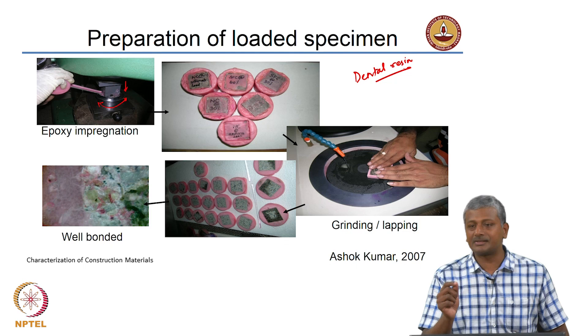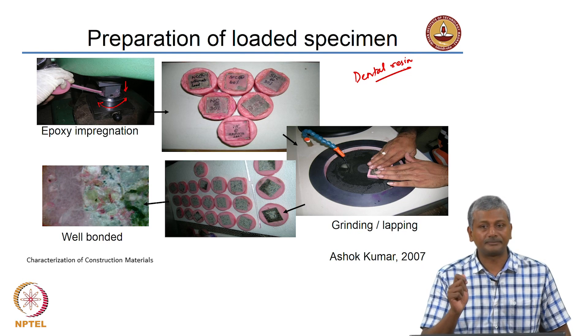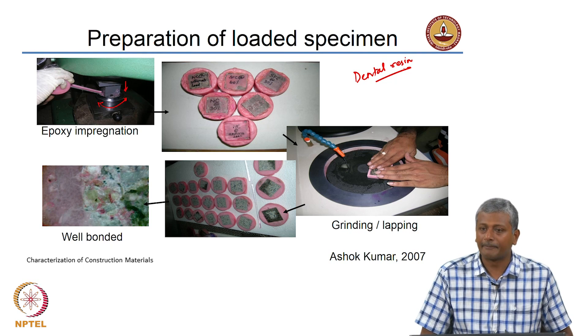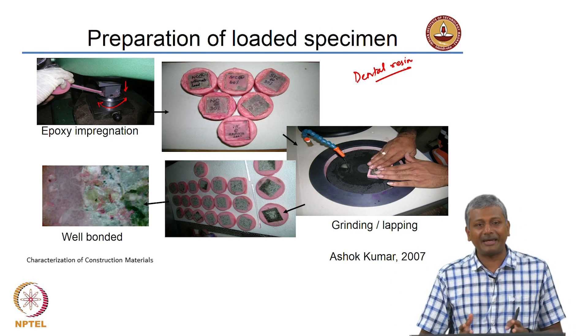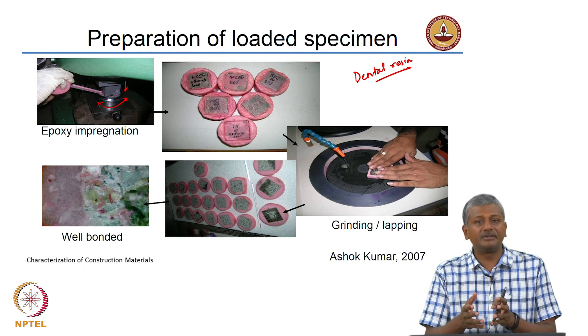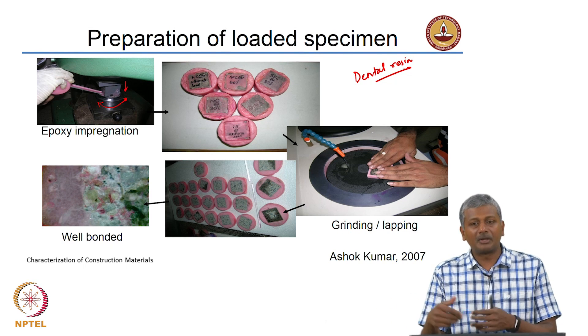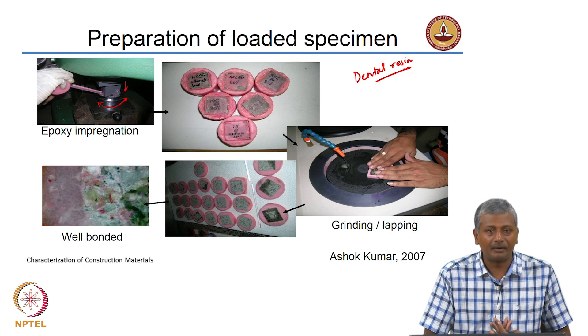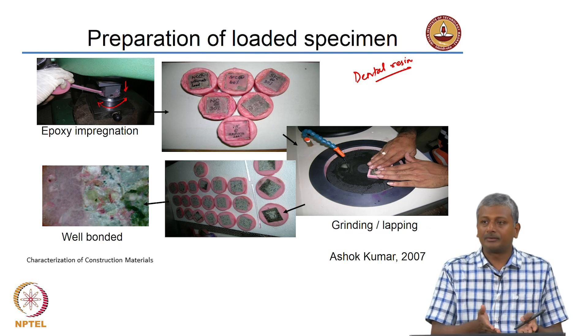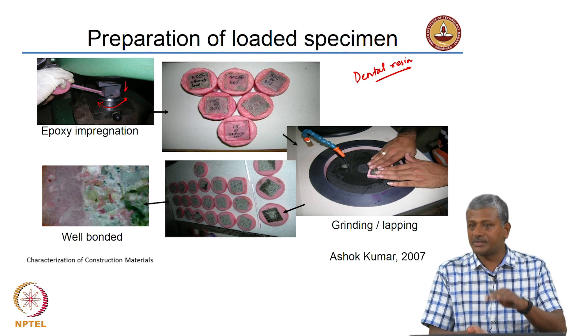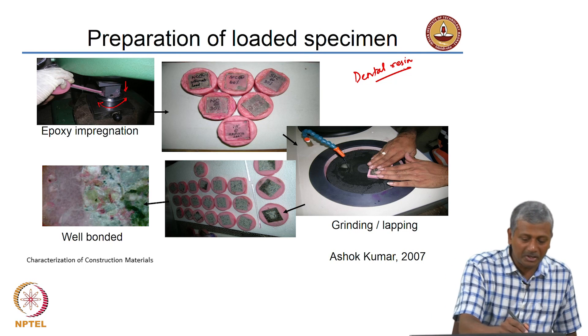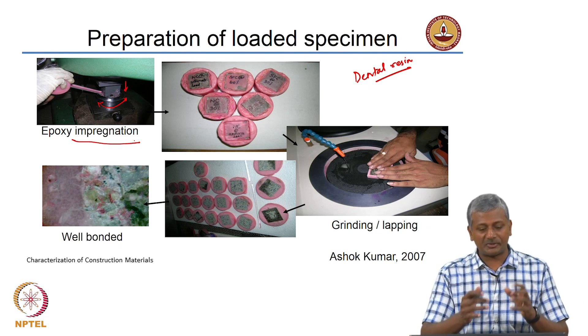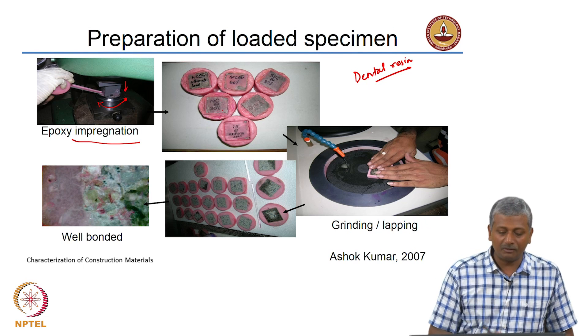The only problem with dental resin is that it is a high-viscosity material, meaning it will not penetrate into the pores very well. Our aim was primarily to preserve the structure, and a lower-viscosity material would have been better, but that takes longer to cure and we did not want to wait long while the loading was still on the specimen. So we encapsulated — rather than impregnated — the specimen in the epoxy, then sliced and polished the encapsulated specimens.